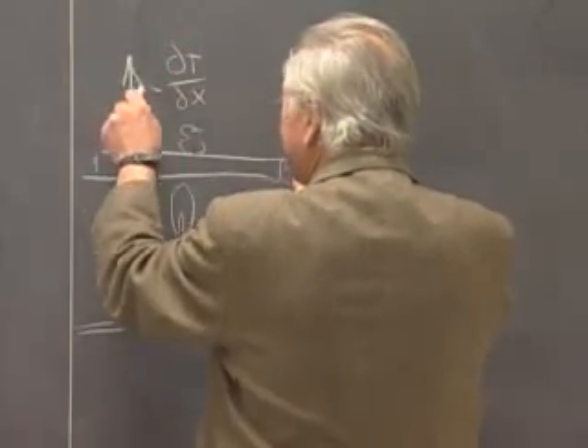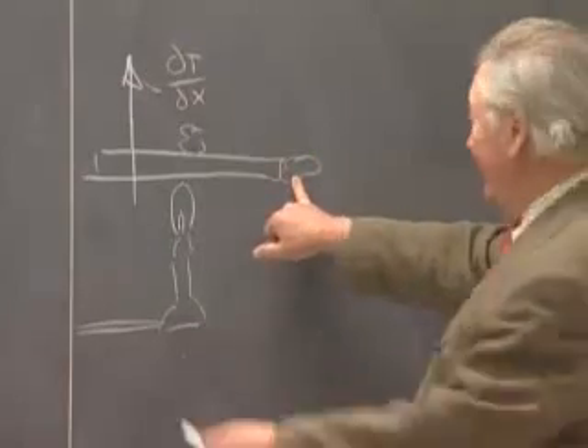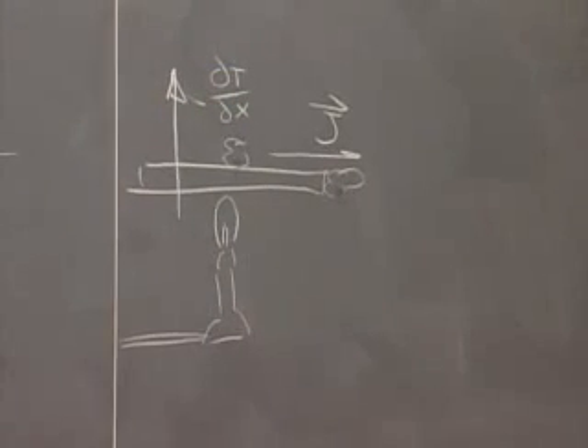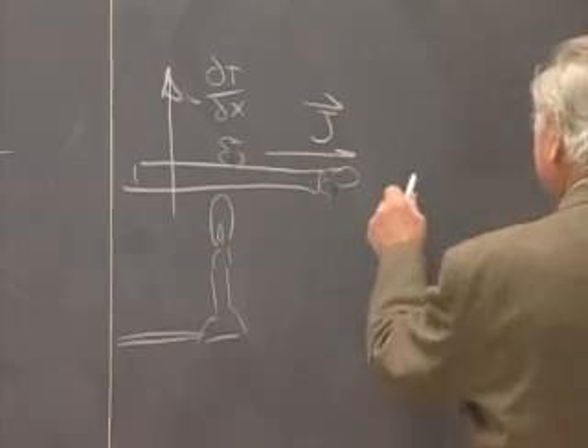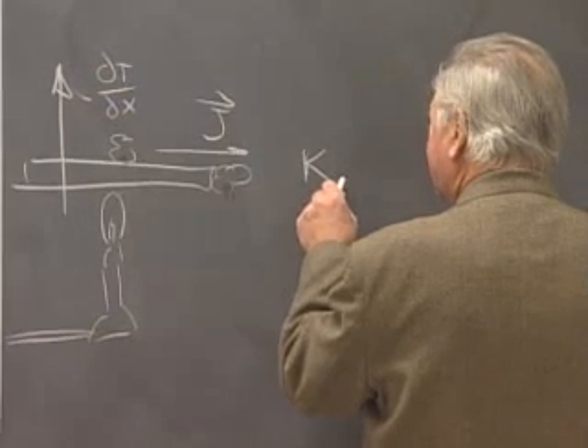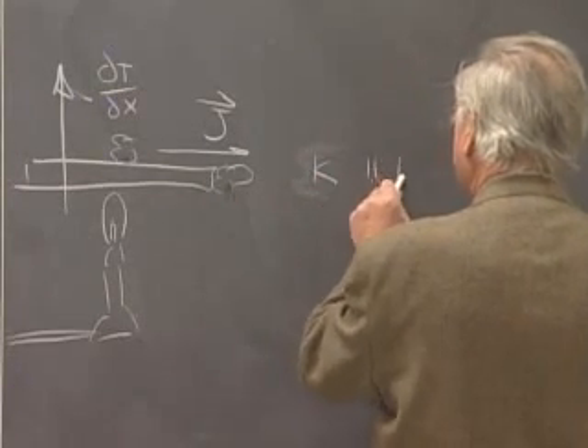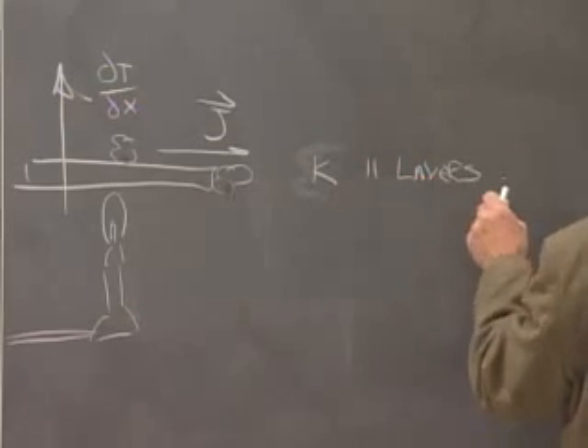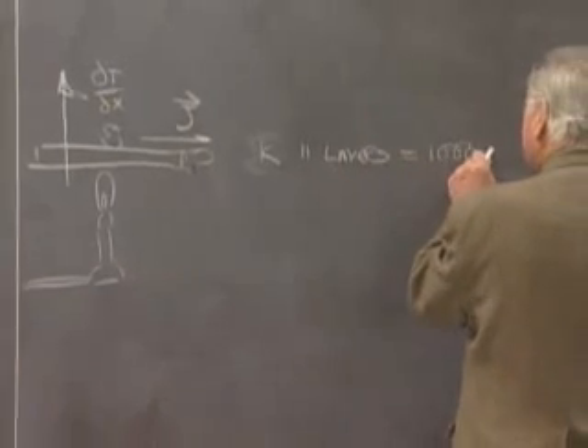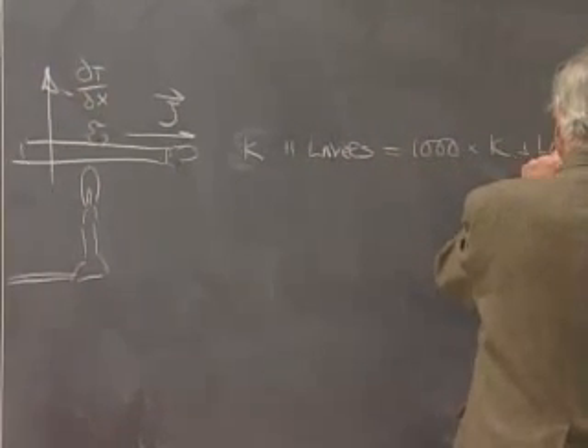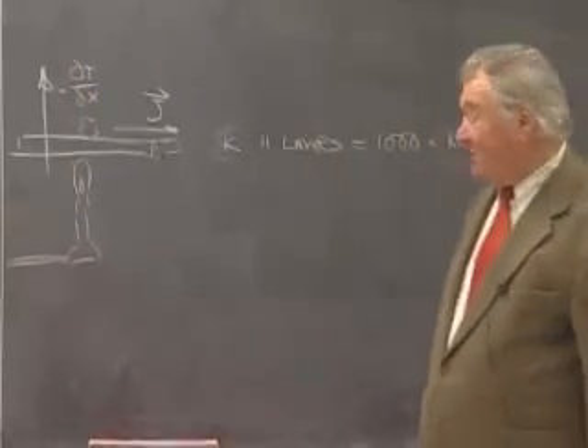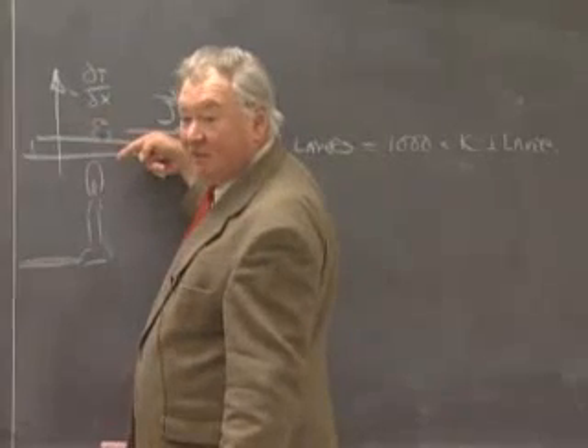So here's a case where dT/dx, the thermal gradient, points in this direction, and the heat flow goes off in a direction at right angles to the temperature gradient. Almost exactly at right angles. It turns out that the thermal conductivity in this direction, the value of K, can't put crystallographic directions on this, but K parallel to the layers is equal to 10 to the third times K perpendicular to the layers. So there's an anisotropy of the property that amounts to a factor of 1,000.